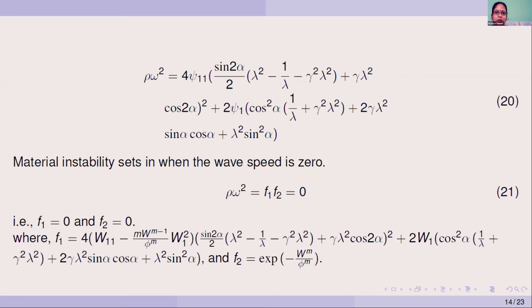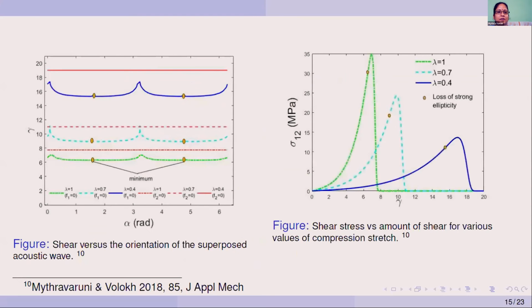And we plot these conditions graphically as shown in this figure on the left. Here these horizontal lines represent the F2 equal to 0 curve, and these other three curves are for F1 equal to 0. And we can see that the lowest amount of shear strain occurs at an angle alpha of 90 degrees and 270 degrees. That is to say that the crack localizes in a horizontal direction, or the x1 axis. These three sets of curves are for three different values of compressive stretch lambda: 1, 0.7 and 0.4. And we can see from this figure that as we increase the compression, that is when lambda equals 0.4, the critical shear strain magnitude is the highest.